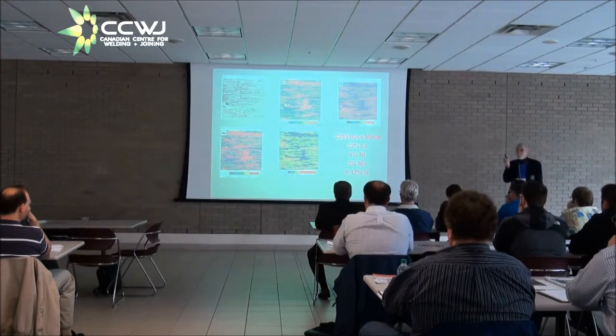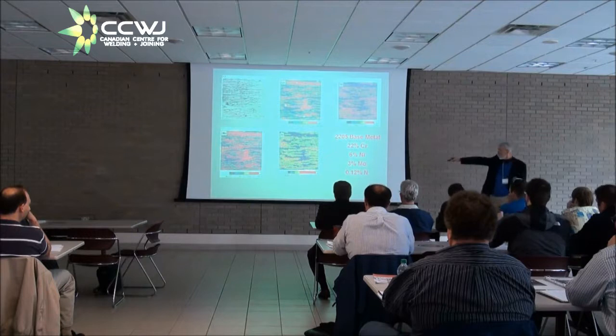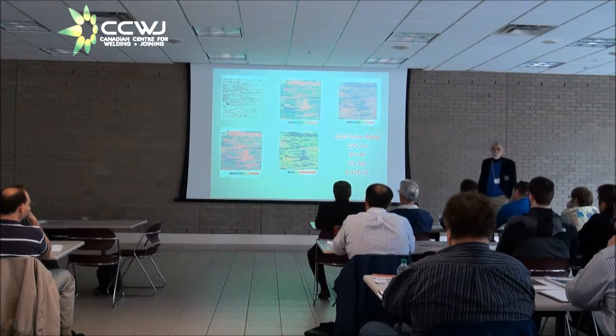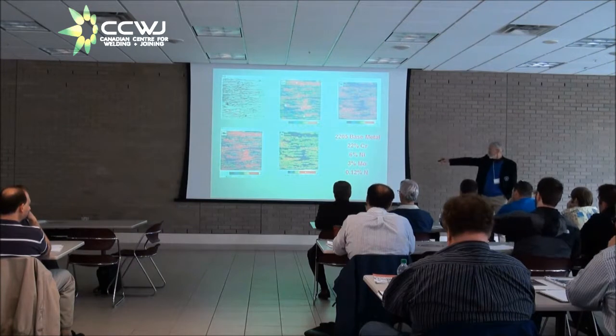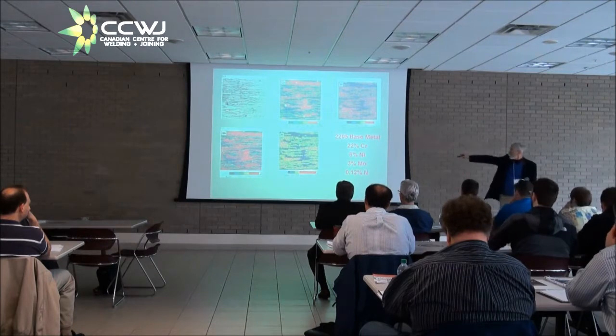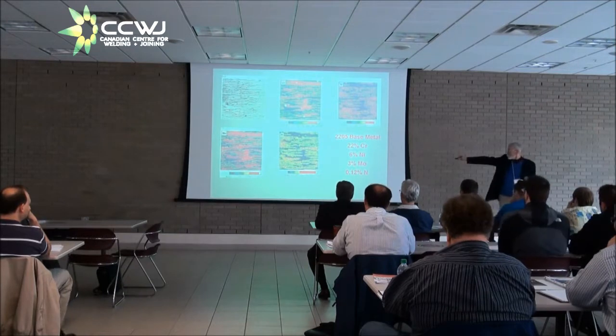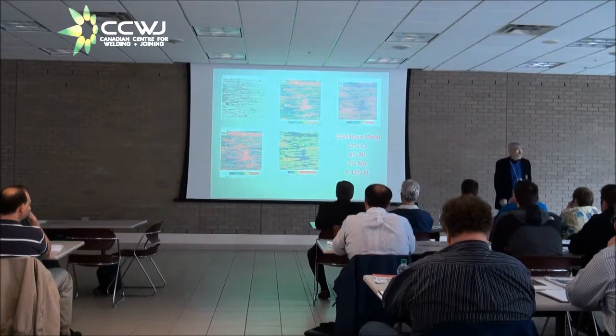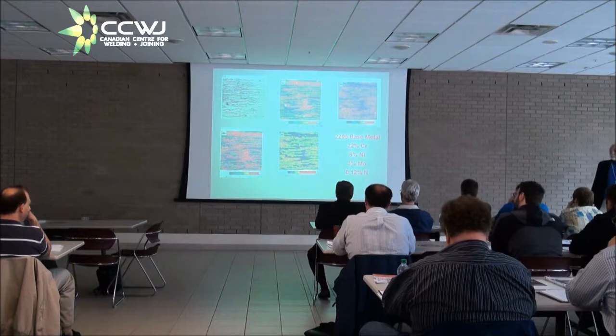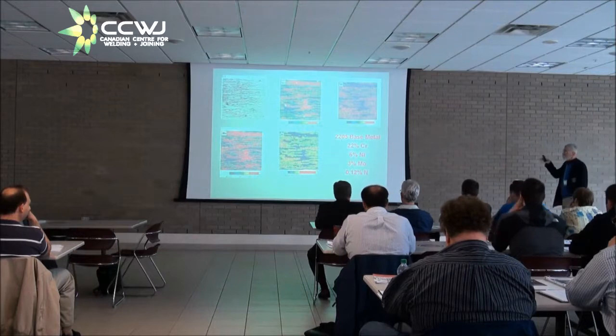The most interesting alloy element, however, is the nitrogen. Now in the nitrogen color coding, blue corresponds to 0. Red corresponds to about 0.25, 0.3, something in that order. And if you look in the ferrite areas, it's 0. If you look in the austenite areas, it's around 0.2, 0.25 for an alloy that contains 0.12% nitrogen. So it's an almost complete partitioning of the nitrogen to the austenite and away from the ferrite.